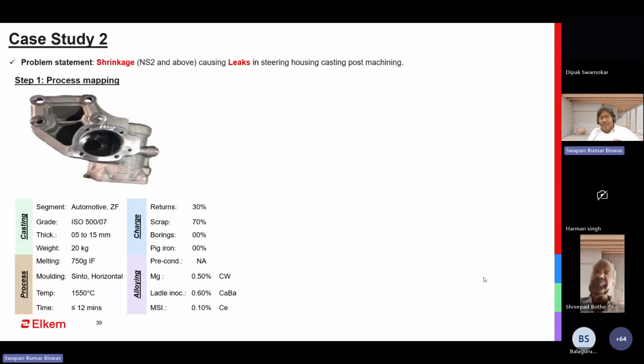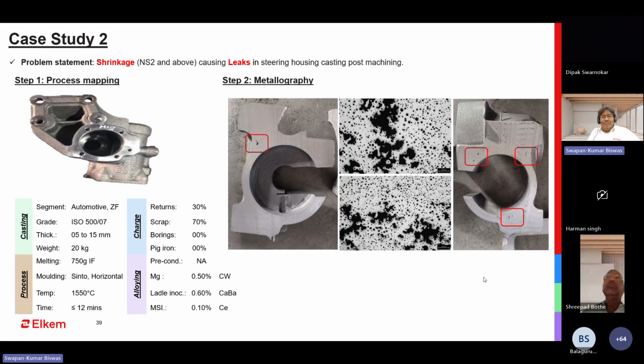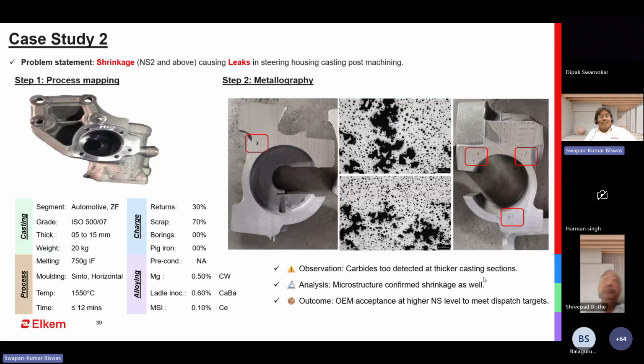There is one more study. There are a lot of studies, but given the time constraint I'll go through only two. This is also about shrinkage and leakage. They found this in the pressure test. So this is the structure. When they are using cored wire treatment, scrap addition is around 70% and 30% return. In the ladle, they are using around 0.6% calcium barium, and the cored wire addition is around 0.5. For inoculant, they are using 0.1% cerium-based inoculant. This is the structure.